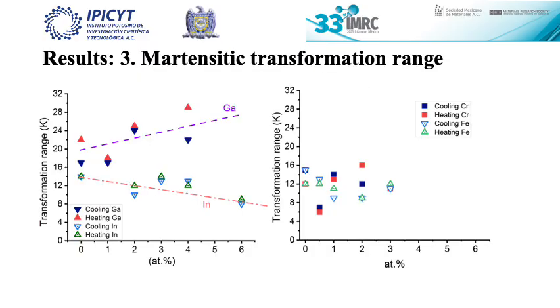For the martensitic transformation range, for gallium, we can appreciate that those ranges rise with the atomic percent. And for the indium, we can appreciate a decrease of those transformation ranges. For the chromium and iron, we can see only a smaller transformation range for the lower composition of those fourth elements.